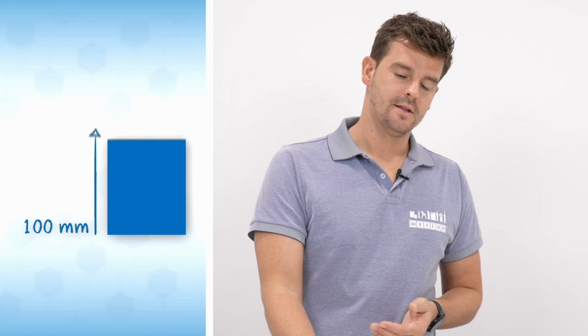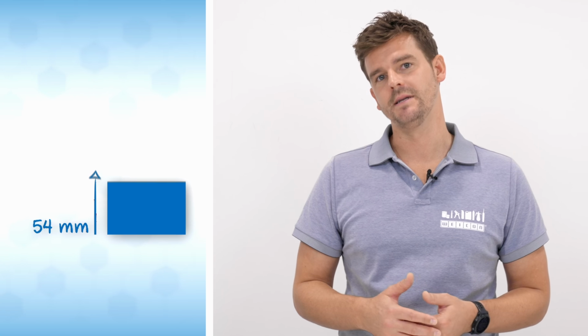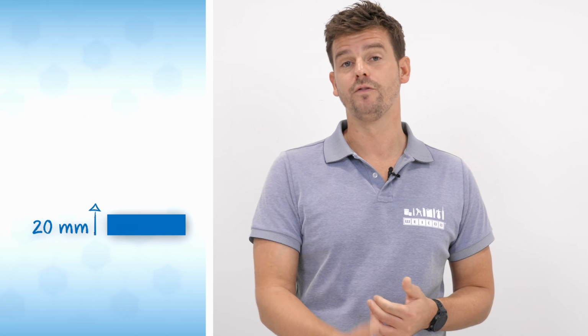Our plastic metal is perfect for the precise and stable gap compensation. It ensured that the grinding plant was up and running again smoothly in no time. The service life of this crusher has been extended considerably owing to the fact that WEICON WR is applied at regular intervals. Let me illustrate this for you. The surface wears from 100 millimeters to 20 millimeters within 4 months. So the repair is necessary 3 times per year, and each time using 20 kilograms of WEICON WR.